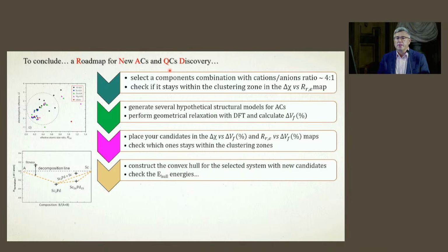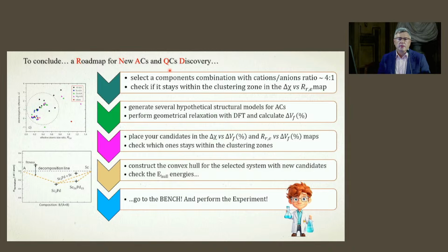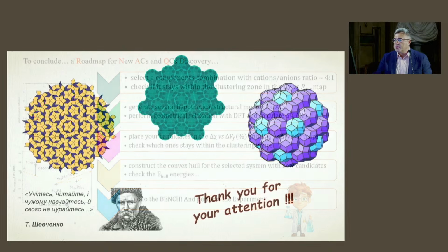Probably you will find a good candidate. If it's only a few millielectron volts per atom, probably you are going toward a successful experimental work to be conducted later, and you can verify your hypothesis by doing an experiment. And probably you would be lucky to discover a new approximant, and if you are so lucky, also a quasicrystal in this system. So I've reached the end of this presentation.